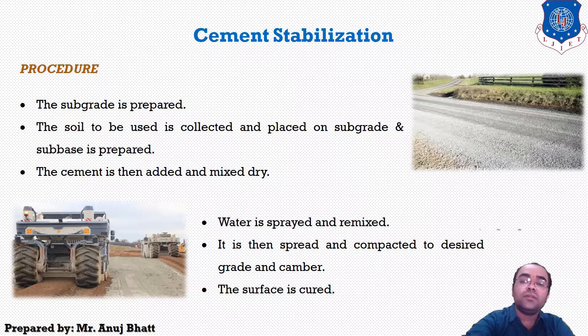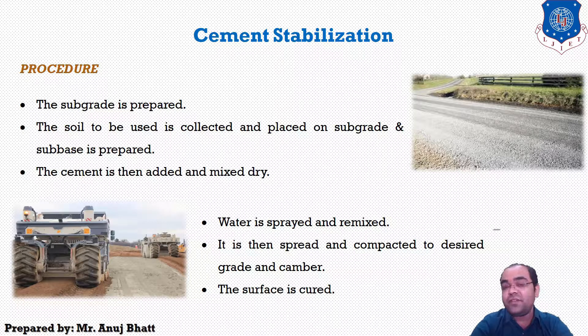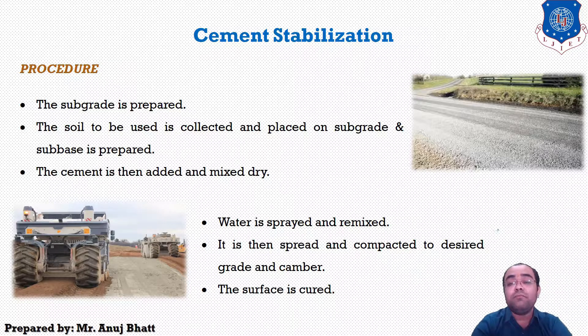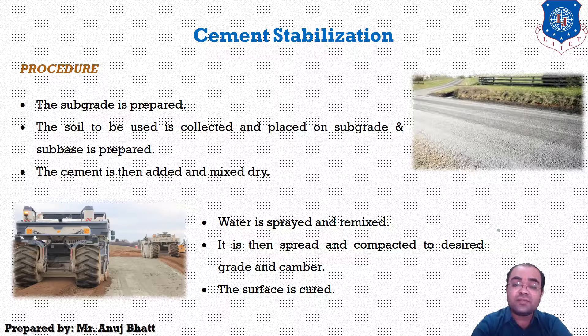For the cement stabilization construction procedure, first the subgrade or sub-base is prepared. The soil to be used is collected from nearby borrow pits and pulverized in a mixing plant. Then cement is added and mixed thoroughly, after which water is sprayed and the mixture is remixed.